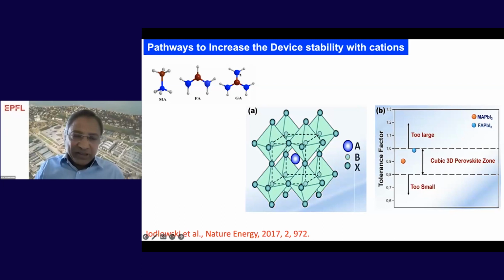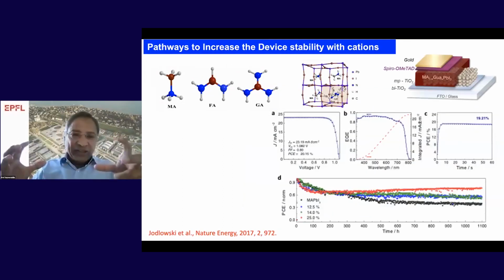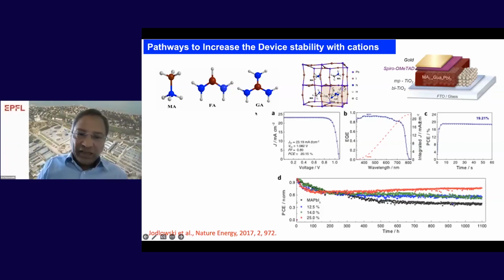But if you look at the size of guanidinium, it is slightly at the edge of 3D perovskite formation. So if we have pure guanidinium, it will not form a three-dimensional perovskite, it will form a low-dimensional perovskite. So what we have done is, can we combine this larger guanidinium cation with the smaller methyl ammonium cation in a particular ratio, for example, 75% methyl ammonium iodide and 25% guanidinium. These are simulations based on DFT calculations. You can see the guanidinium is inserted in the cubic cell, where the guanidinium cation is interacting with iodides. Therefore, this particular unit cell is stabilized because of enhanced hydrogen bonding.